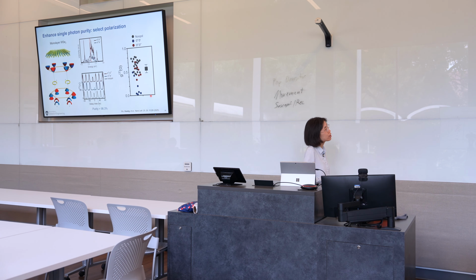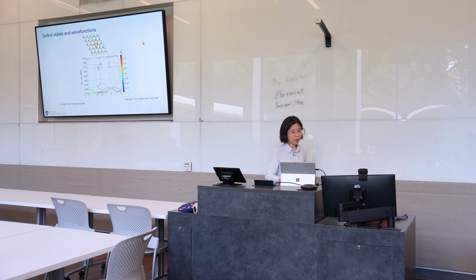Now, if we summarize the G2 we measured for all of these spots, you can see there are several G2 that have very small value. All of these correspond to the cross polarization case. Now, if we look at the first principles calculations, we can find the evidence.